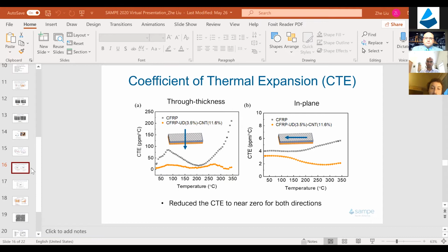First, the coefficient of thermal expansion. If there's a very weak bonding surface between our thermal shielding layer and the composite, then with the temperature going up, there might be some break or delamination between the bonding layer and the substrate composite. We tested the CTE to know the expansion of the composite in the in-plane direction and through the thickness direction. From both results, we see that without the thermal shielding layer, the composite CTE goes up with the temperature. That's because the polymer chain has more movement space after the Tg.